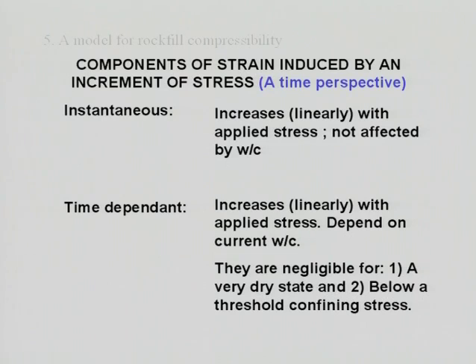However, the time-dependent strains also seem to increase, linearly or not, this is not fundamental, with the applied stress. But what is fundamental is that they depend on the current water content. Also, we found that those time-dependent strains are very small if we have a very dry state, and they are also very small below a threshold confining stress.